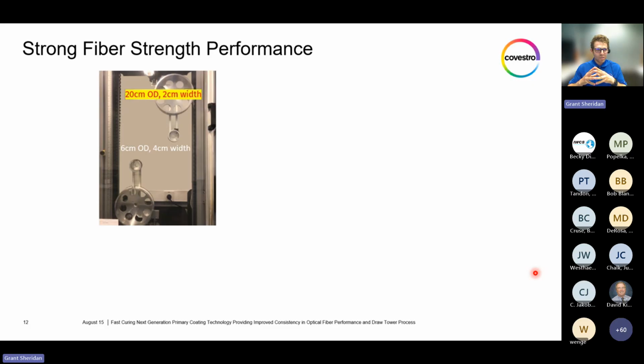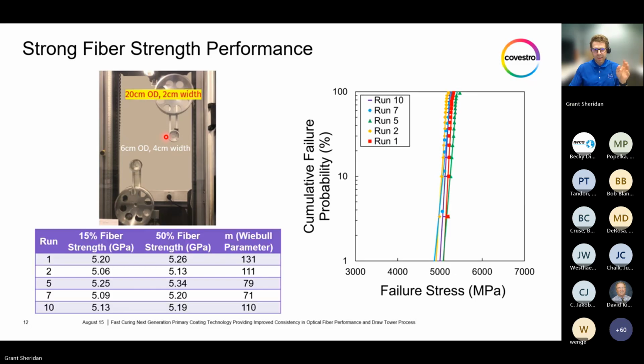In addition to the low temperature microbending performance, we also looked at the fiber strength. Previous IWCS publications had demonstrated or raised the concern of the effect of high draw speeds on fiber strength. So shown here is just a quick overview of our fiber strength testing conducted with two capstans. So we have a 6 and 20 centimeter diameter capstan.